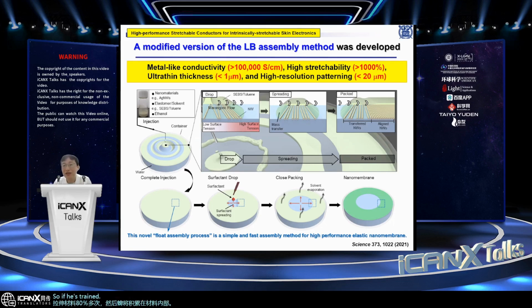So if we stretch that material once, that may be fine. But if we stretch multiple times, due to the fatigue accumulation, eventually mechanical failure will occur. However, if the maximum stretchability is 1,000%, and if we stretch the material only 80% multiple times, then the stretching amount of 80% is much less than the 1,000% maximum stretchability. Although we stretch the material multiple times, the fatigue accumulation can be minimized. That's the reason why we want to achieve very high stretchability.